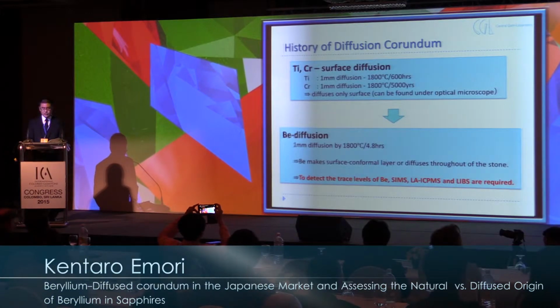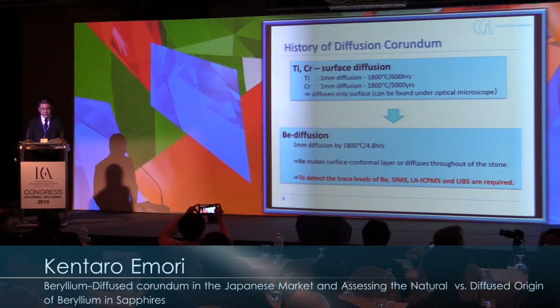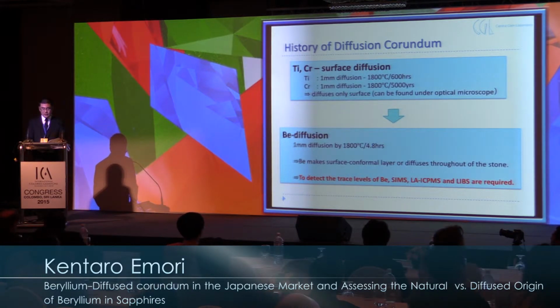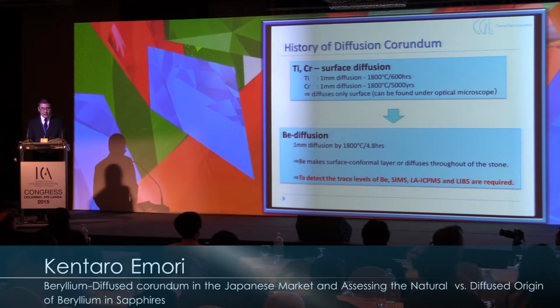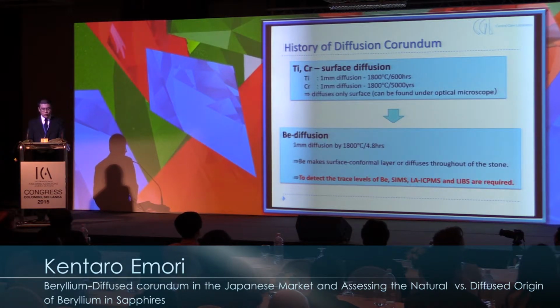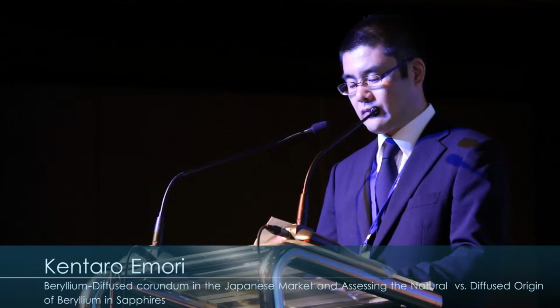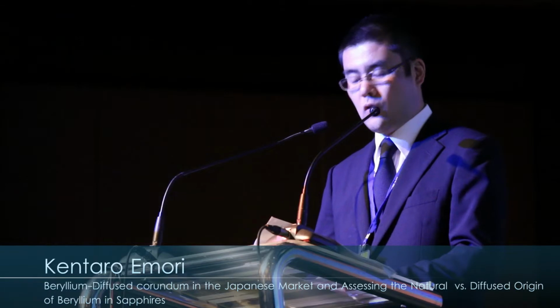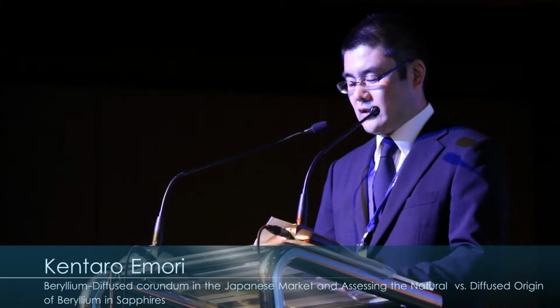In diffusion from outer sources, before the appearance of beryllium diffusion treatment, there was a surface diffusion treatment using titanium and chromium. It takes 600 hours at 1800 degrees Celsius for 1 millimeter diffusion of titanium and 5,000 years for chromium. Since the diffusion rates of titanium and chromium are extremely low, they diffuse only at the surface of a crystal, thus can be observed under an optical microscope.